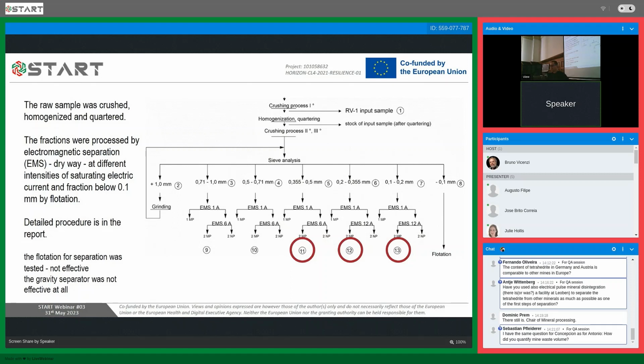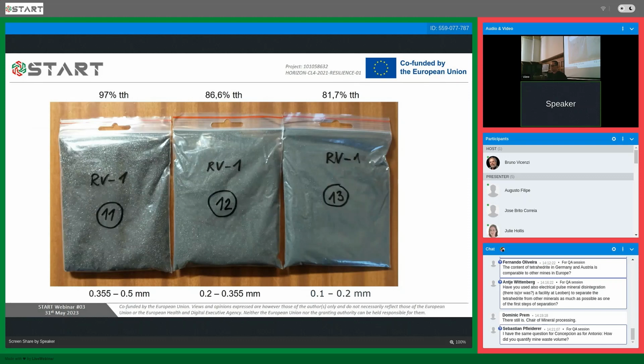Flotation for the separation was also tested, but it was not effective, and gravity separation was not effective at all. Here is how the final concentration samples looked. They are in different grain sizes, from 0.1 to half a millimeter, and the amount of tetrahedrite in these samples varied from 82 to 97% of tetrahedrite.